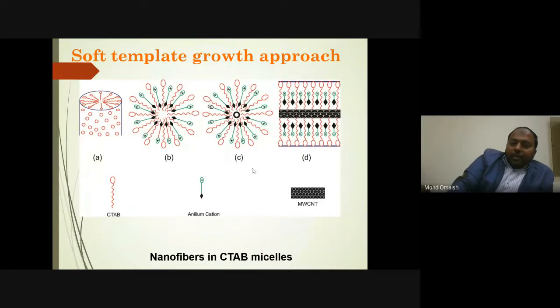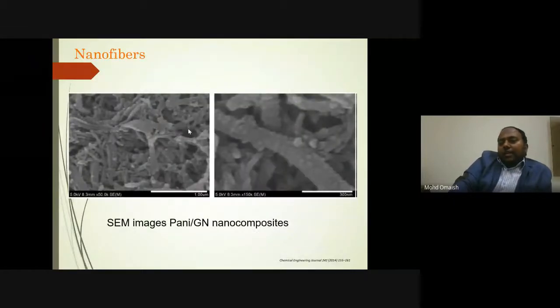The polymerization is done in the micelle. Surfactants have a tendency to form micelles at a particular critical concentration, called the CMC. At that concentration, they can act as a directing agent for the polymerization of aniline monomer or pyrrole monomer, and we can get a directed morphology. For example, we can get an elongated tube. Apart from this, temperature and pressure are also very important. So we can get a directed morphology like this. In this case, we got nanofibers.